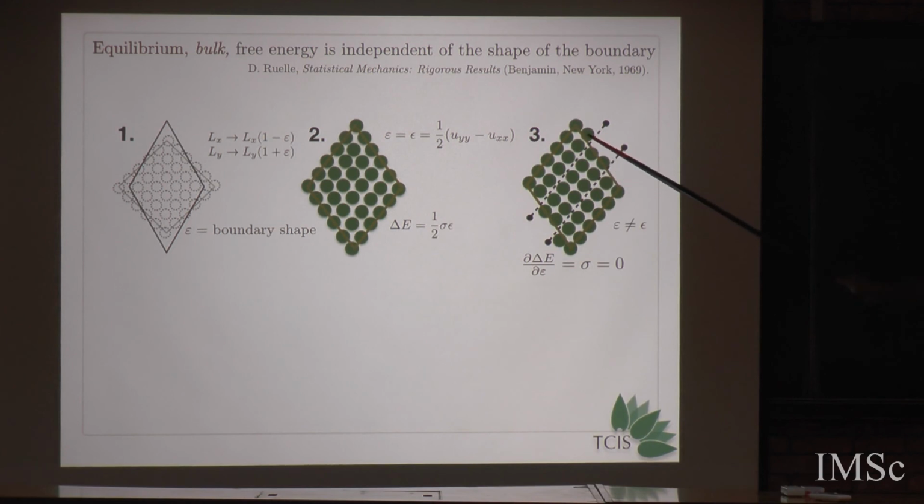So the boundary is respected, but inside the bulk there is no stress, there is no strain, and the energy is actually zero. So in this case, the elastic strain is zero. So what this solid has done is to trade a bulk stress or a bulk energy for a surface energy.